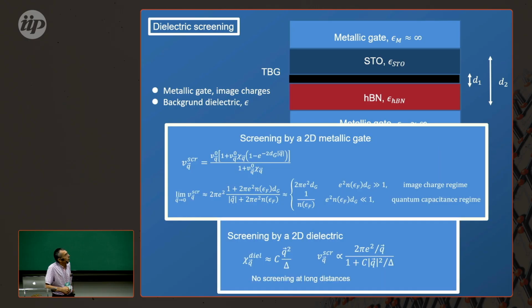The screening by a two-dimensional metallic gate can only be described in terms of image charges if it is really a perfect metal with an infinite density of states. Otherwise, there are quantum corrections you have to worry about. So if your gate is a graphene bilayer or even a few layers of graphite, then you have to worry about that. And a two-dimensional dielectric is not a real dielectric.